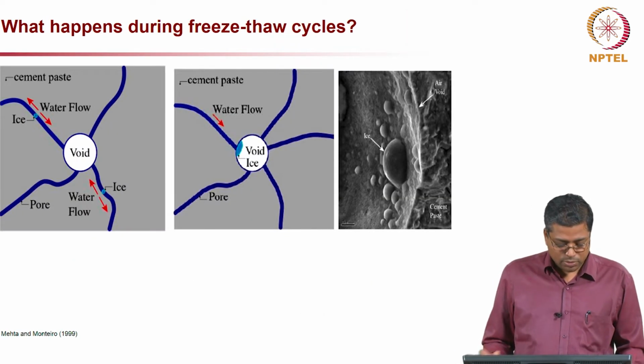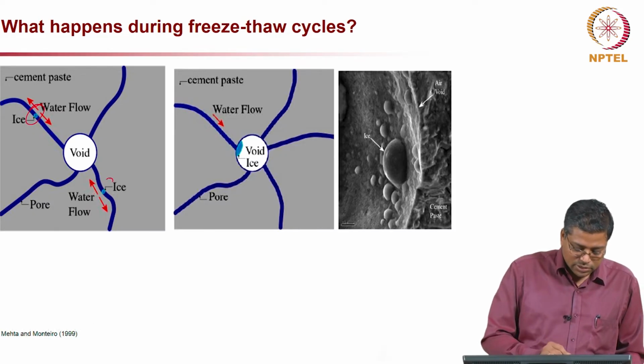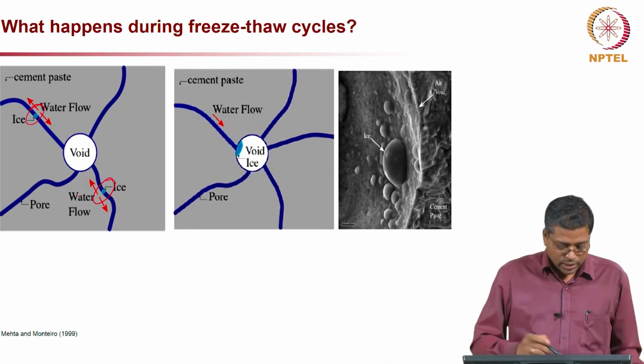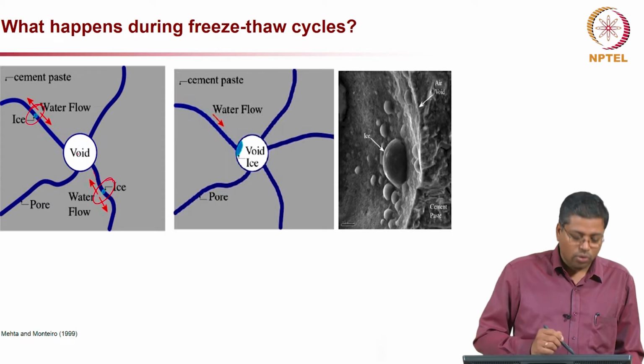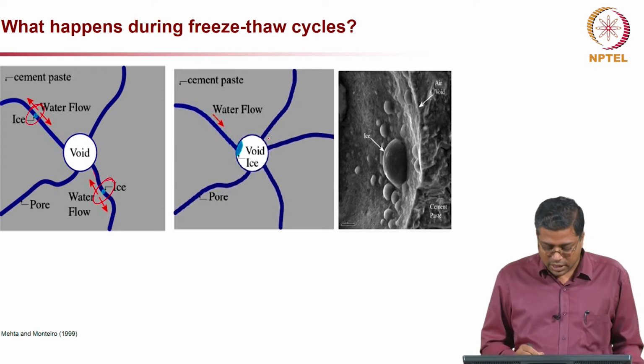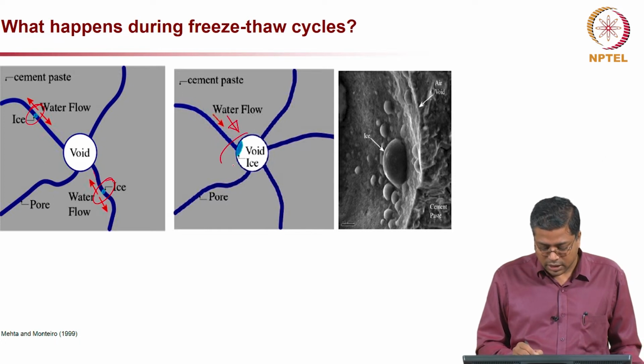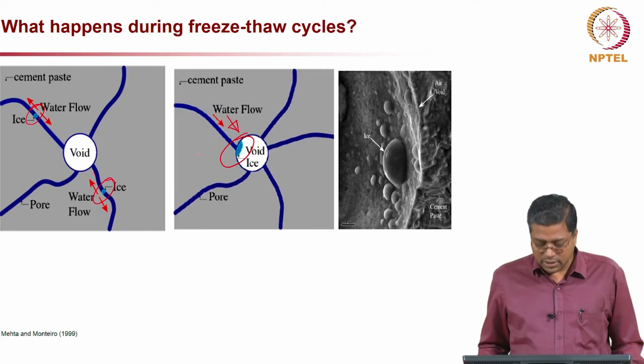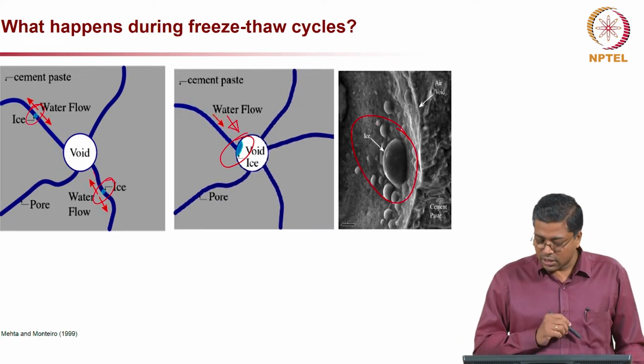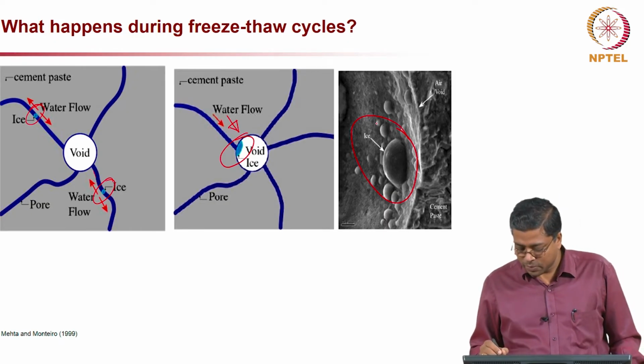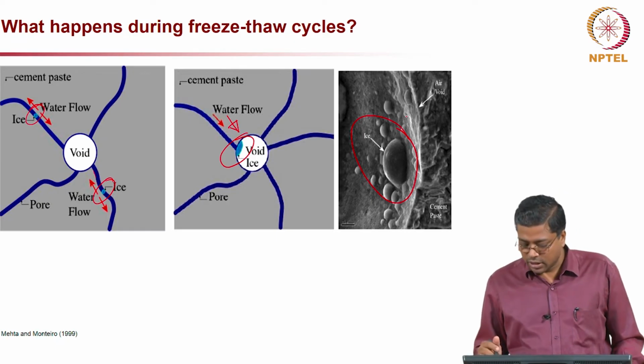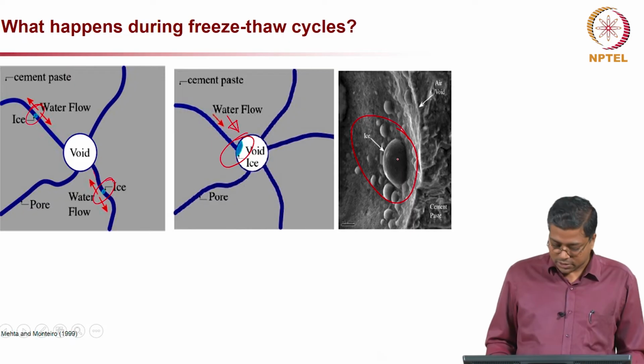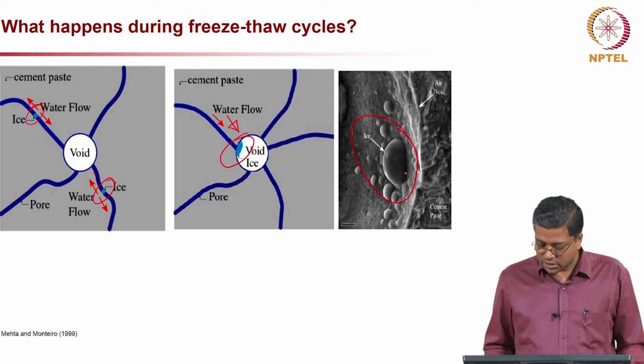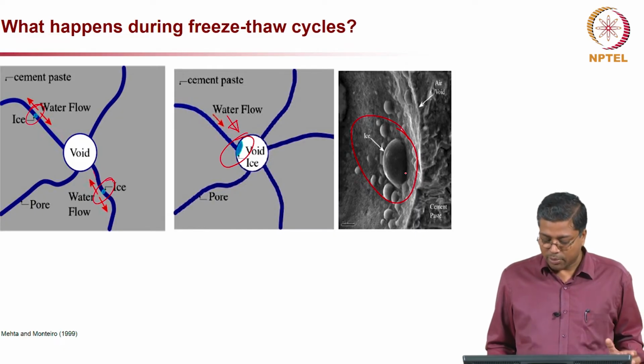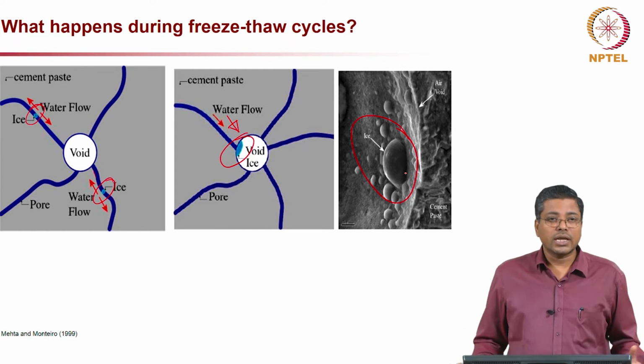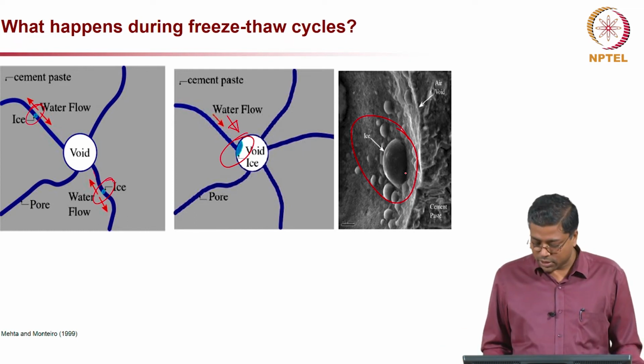So, this is what I just mentioned. Here you can see a little bit of ice is formed, that ice will push the water near there, and this water can actually flow into the void, and if that void space is nearby, you can see here water is flowing to this, and then a small ice is formed. The picture on the right end shows how this ice is formed. This is one of the classical images from Berkeley, where they have captured this ice formation inside the air void in cement paste. Very nice image. You can see a lot of ice formation happening, and so this is what really happens. So, if you have an air void, then it will not exert pressure, but if you do not have air void, then it will exert pressure and lead to cracking.